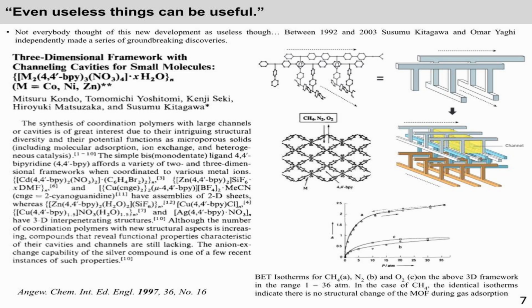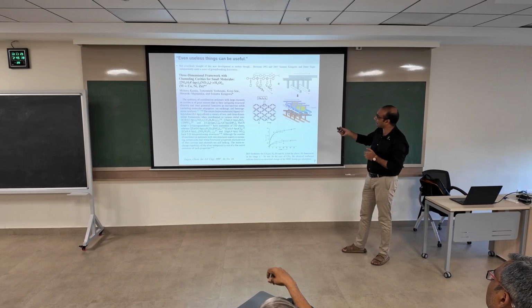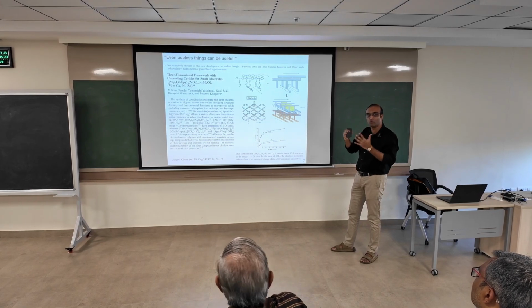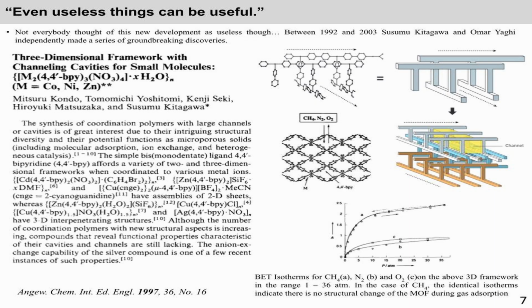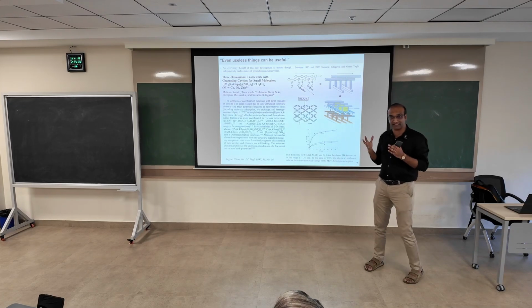But this is the first time where you could make this breathable morph, where it could rotate, with these interlinking channels. There's a channel A and a channel B, which are orthogonal to each other. And they could basically move with the way the gases are flowing in and out of them. It is not that stable, but it was more stable than whatever was happening before. And it was stable at pressure also. So they could trap these gases and see that the structure was still stable after use.